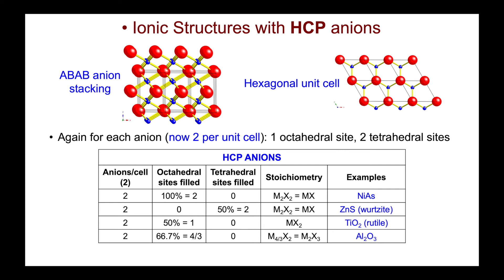We can go through possible stoichiometries for different fillings. Filling all octahedral sites gives stoichiometry M₂X₂ = MX, which is the nickel arsenide structure. Filling half of the tetrahedral sites — two of four total — gives stoichiometry MX, which is the zinc sulfide wurtzite structure. Filling half of the octahedral positions gives one cation per cell, stoichiometry MX₂ — the rutile structure, which is one of the forms of TiO₂.